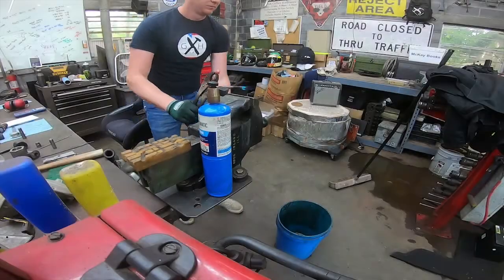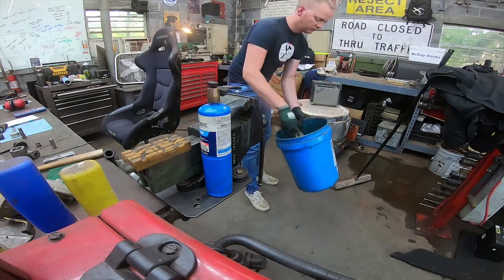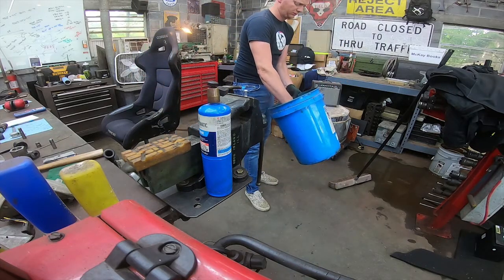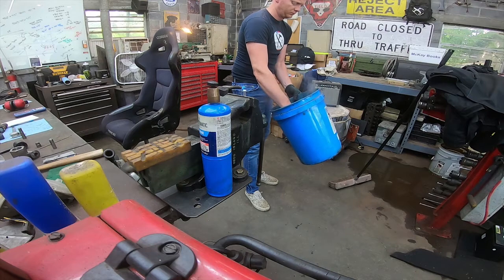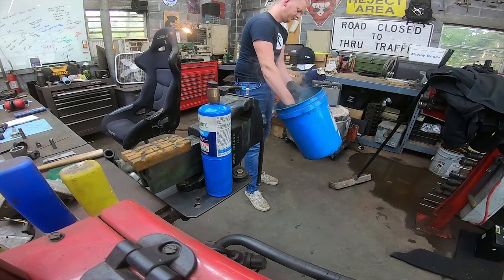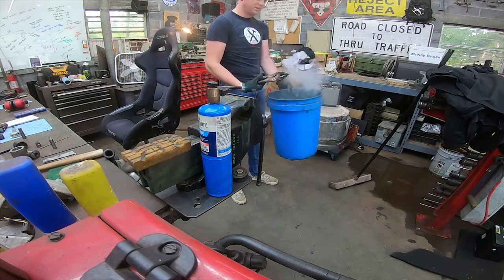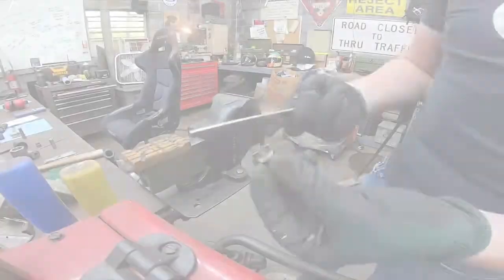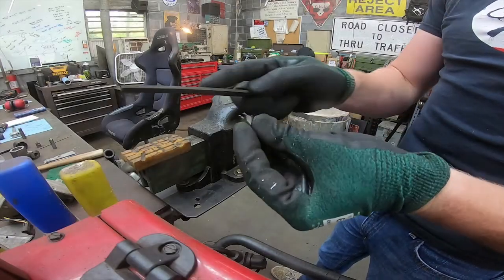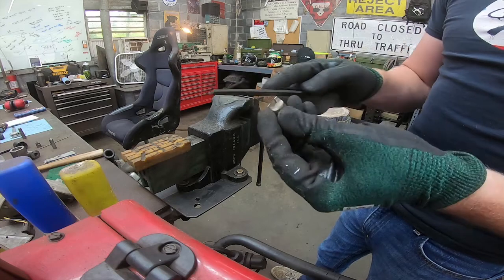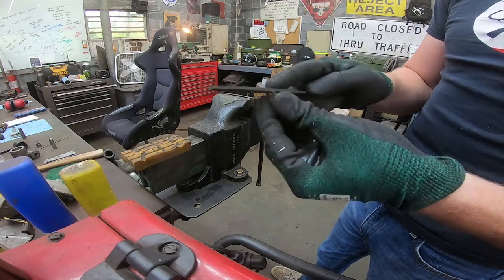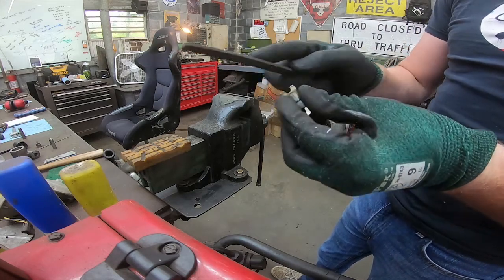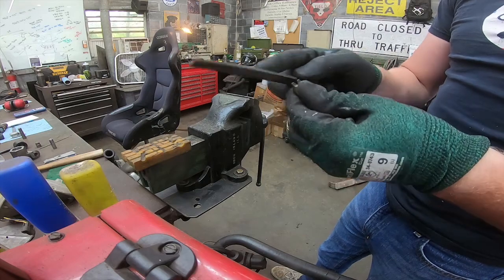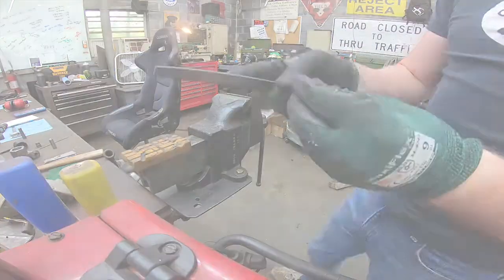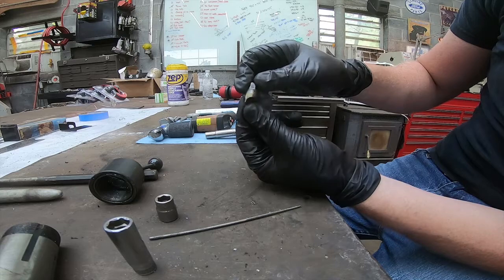And here we are going for the quench. So one thing to notice is that this is warm oil. It's Parks 50 oil in that bucket there. And something else, guys, don't be stupid like me and actually use a respirator. You don't want to breathe this stuff in. Alright, and a quick little test to see if the heat treat actually took is if it skates a file. If you listen to that sound and it's not digging in at all, then that's good evidence that it did harden up nicely. And here we are back at the workbench.